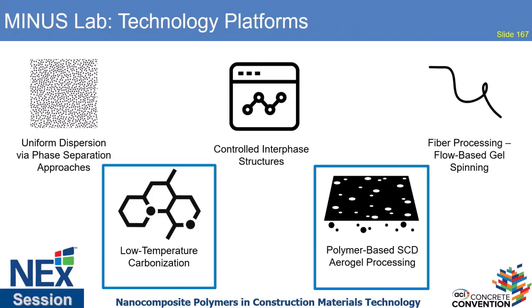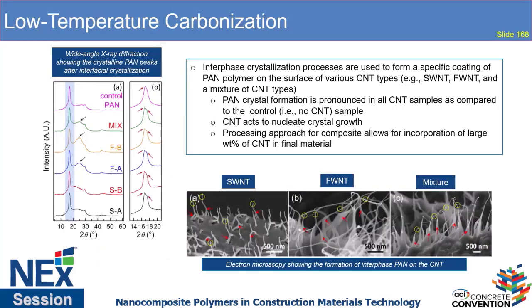So I'll touch on what we've been doing in carbonization, because for carbon fibers, that's why we use a lot of PAN. When you can create these types of interface structures around the nanomaterials, you can do it for a lot of different nanomaterials. So we look at few wall nanotubes, multi-wall, single wall, mixtures. We buy from everyone that makes it, the cheapest stuff to the most expensive stuff. And you can always make an interface structure because you can control the polymer, but will it stay stable under all of the processing conditions is a different story.